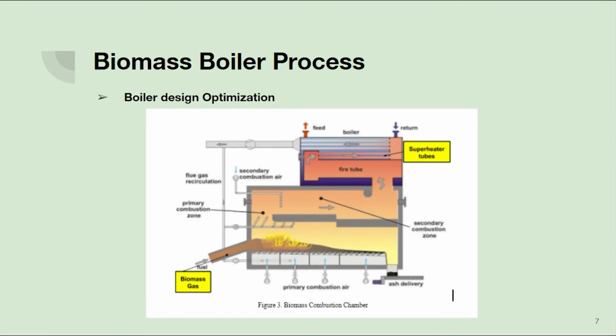Boiler modifications such as adding a radiant pass between the furnace and superheater, installing cooling tubes directly upstream of the superheater to trap chloride deposits, and adding a superheater insulation layer to increase the surface temperature above the dew point temperature of alkali chlorides can also be implemented to reduce corrosion.